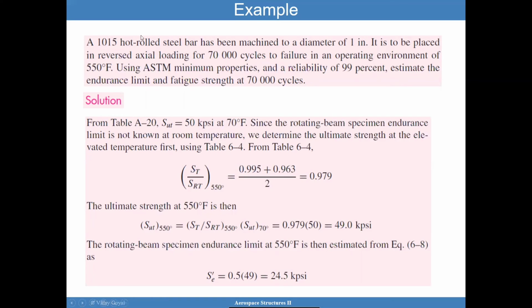So another situation is, I have a hot rolled bar that has been machined to a diameter of 1 inch. It is to be placed in reverse axial loading for 70,000 cycles to failure in an operating environment of 550 degrees F. Using ASTM minimum properties and a reliability of 99%, estimate the endurance limit and fatigue strength at 70,000 cycles.